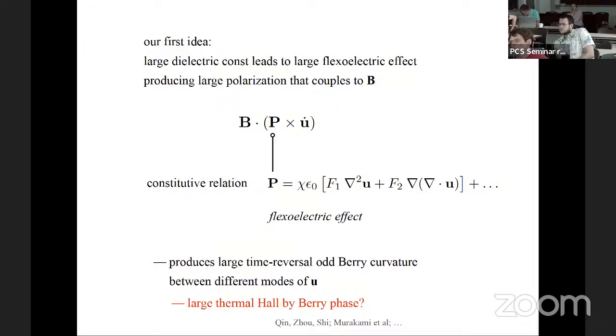This polarization and this constitutive relation can be understood as a mixing, like a rediagonalization between the acoustic and the optical. Because the optical phonon will involve the relative motion of the positive and negative charge. So actually this comes from the optical phonon. It's like a rediagonalization between the acoustic and the optical, right? But the optical phonons themselves do not directly contribute because even if the gap is small, the gap is still 20 Kelvin. But in the experiment you can see the effect at like a few Kelvin, like 1, 2, 3 Kelvin, right? So this u is both optical and elastic. It's rediagonalized, and actually the large coefficient chi here is related to the fact that the mixing becomes enhanced because of the small gap of the optical phonon. Yeah, we can also phrase it that way.